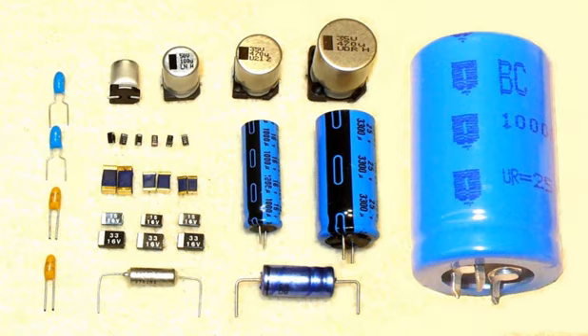Measured with an AC measuring method with 100/120 Hz, the capacitance value is the closest value to the electrical charge stored in the ECAPs. The stored charge is measured with a special discharge method and is called the DC capacitance. The DC capacitance is about 10% higher than the 100/120 Hz AC capacitance. The DC capacitance is of interest for discharge applications like photoflash.